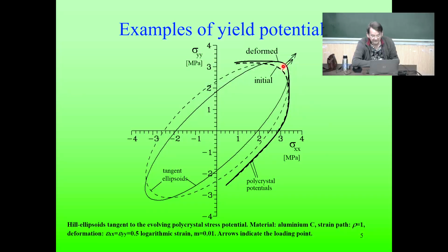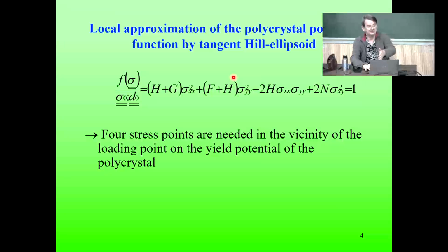Now, after deformation, we trace, here you see, just for showing the polycrystal yield surface, yield potential, not yield surface, yield potential, and the fit with the Hill ellipsoid. You see a lot of changes happening in the shape and the size of the fit. And now, then this is going to be our yield surface. We only need it locally, and then we can use it. We can use the normality rule, associated flow rule, to link the stress state to the strain rate state.